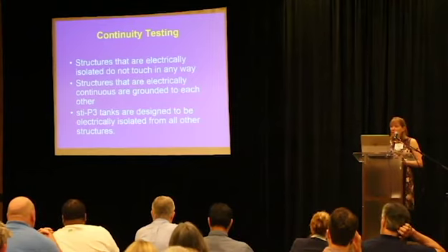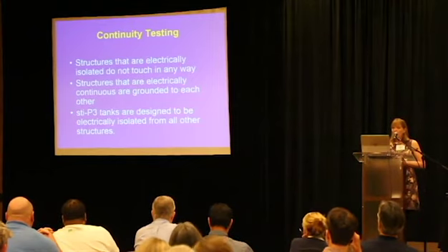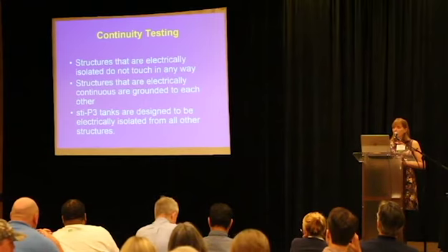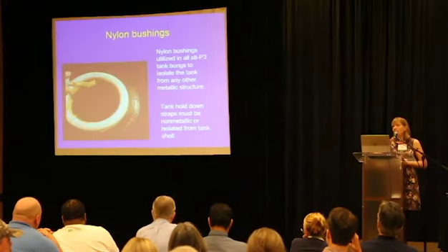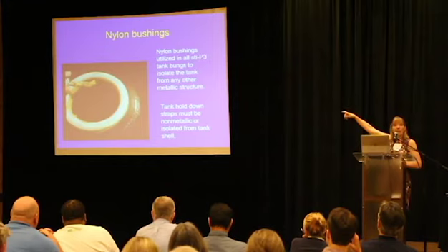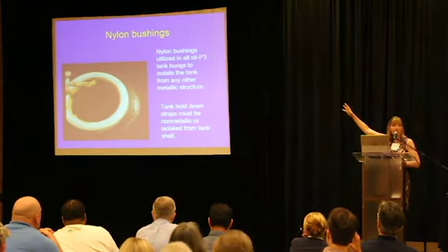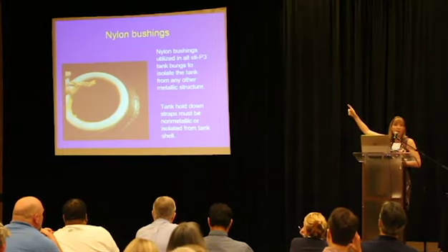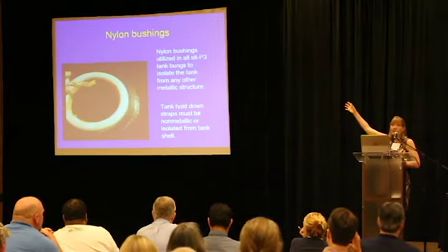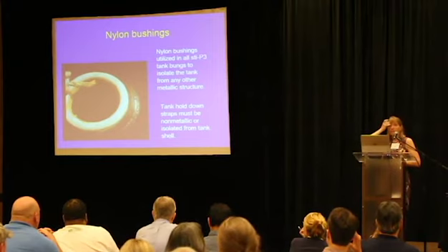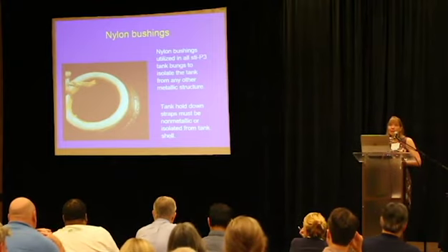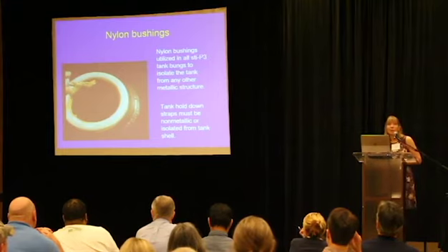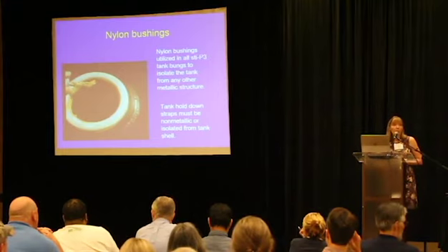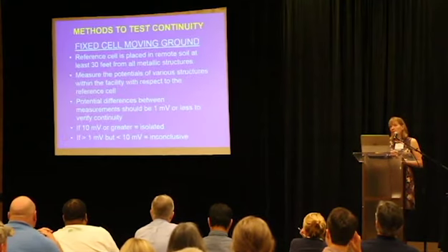Okay, so continuity testing is required for impressed current systems. STI P3 tanks are designed to be electrically isolated. Most of the time, they're going to have these nylon bushings. So if they're retrofitting a P3 tank for some reason to an impressed current system, they should be connecting in those any of the lines above, fill lines, in my opinion. I mean, technically they don't have to. It's not routinely holding product. But if they don't, that pipe is going to corrode. So they have 2 methods of testing continuity.